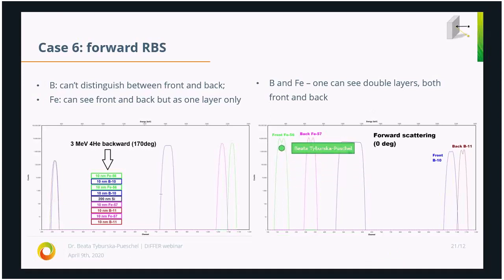If we, however, switch to forward scattering, then here you can see our front iron, and you can see two peaks here on the top. So we can distinguish those two layers in our frontal iron. Then we see our back iron, and again you can see two layers. So those two here, we can distinguish between them. Then we have our silicon in the middle, and then you can see here the back and front boron, and again there are at least some dips in it. And so you can distinguish those layers as well.